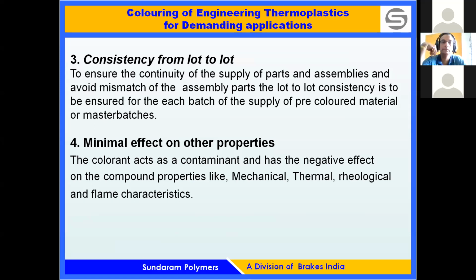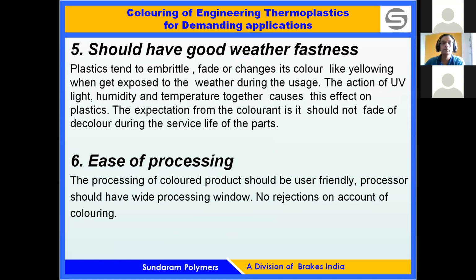We should have very good weather resistance. The color has to last long. Plastics tend to embrittle, fade, or change when put into service conditions. Yellowing can happen when exposed to the weather during usage. The action of UV light, humidity, and temperature together causes this effect on the plastic. The expectation from the colorant is that it should not fade or decolor during the service of the part.